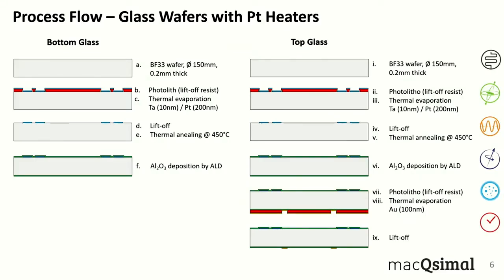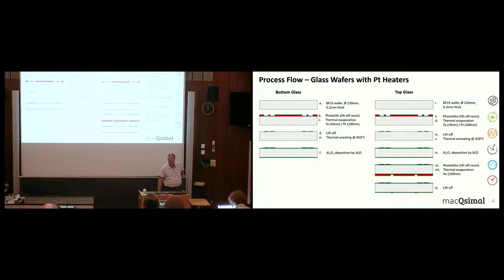Then in parallel, we fabricate glass wafers for the bottom glass and for the top glass. Here we start with, again, 150 millimeter diameter glasses, but of borofloat. They are only 0.2 millimeter thick. We do a first photolithography with a lift-off resist, and then we deposit by thermal evaporation a thin adhesion layer, tantalum 10 nanometers, and platinum 200 nanometers. So this is in the case where we want to have a resistive heater on top of the cell. Then we do a lift-off process, and we end up with the metallic pattern. We make an annealing to stabilize the resistivity, and at the end we deposit again by ALD process an aluminum oxide, again as diffusion barrier for the rubidium.